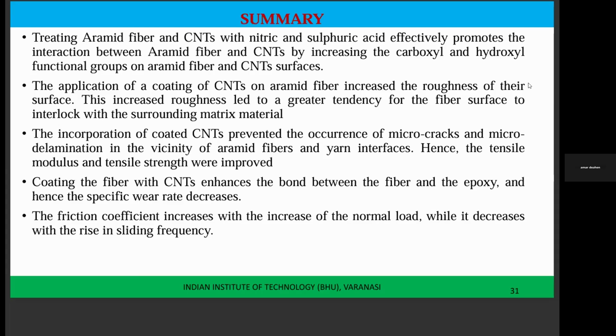Finally, when we are treating with the aramid fibers and also CNTs, you can see an enhancement in the strength, a reduction in the coefficient of friction, and a reduction in the specific wear rate. The friction coefficient increases with increase in the load, but decreases with the rise in the sliding frequency. Next slide, please.